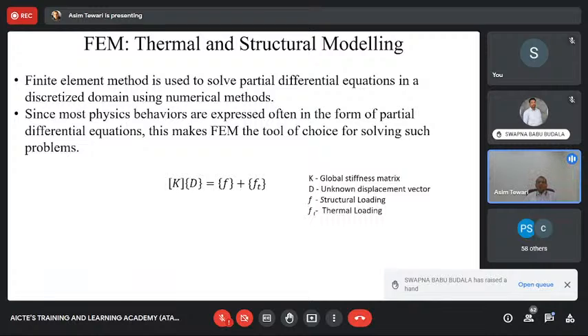So the finite element can be used to model both the heat transfer and the thermal aspects as well as the structural aspect. And they need not be fully coupled, which means that the heat transfer can happen independent of the structural modeling. The reason is that the heat transfer is not a fully coupled model, which means that the heat transfer is not being changed because of any structural variation. However, structural variation is certainly changing because of heat transfer. So this is a one-way coupling of heat thermal modeling to the structural modeling. That makes life much simpler.